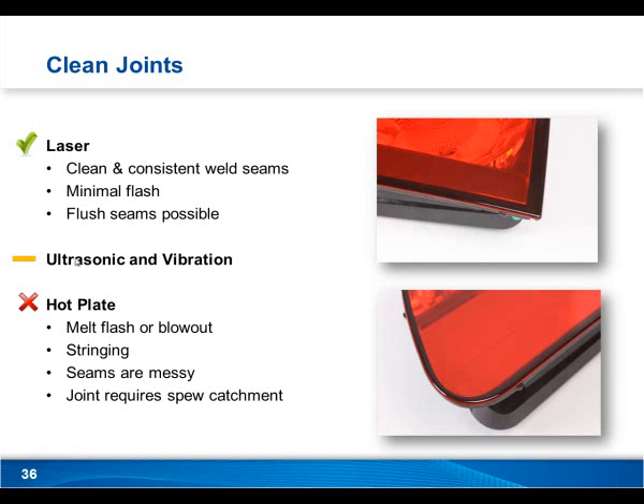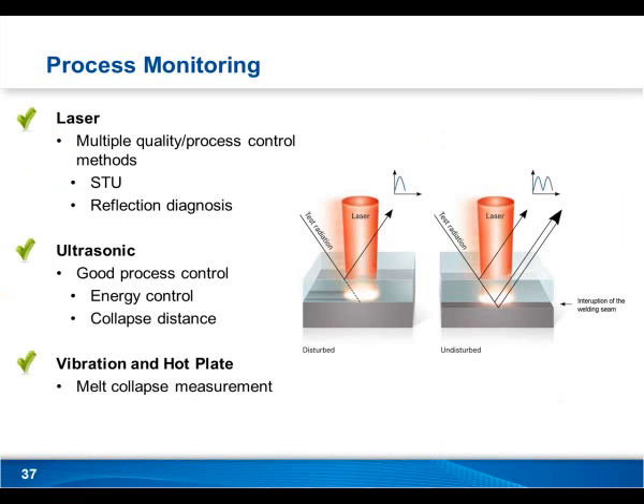Ultrasonic and vibration, they provide relatively clean joints, but you do see more melt flash than you'll see with laser welding. Hot plate, you're going to see a lot of melt flash and blowout, and stringing is the most common issue we hear about with hot plate. So, process monitoring, this is always really important as you talk about production level assembly. Each one of these methods do tend to have good process control, so I really just wanted to bring up laser welding's ability to monitor its processes.